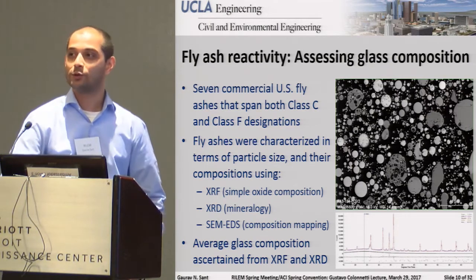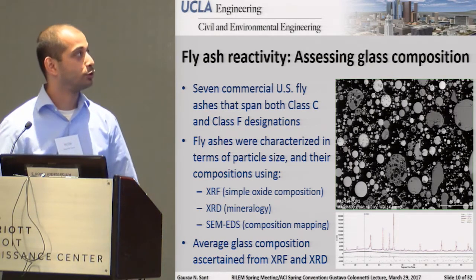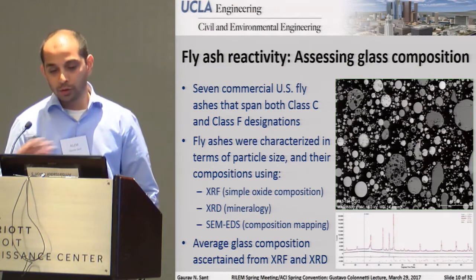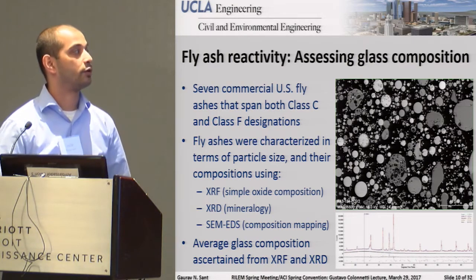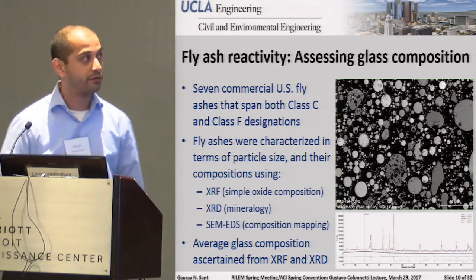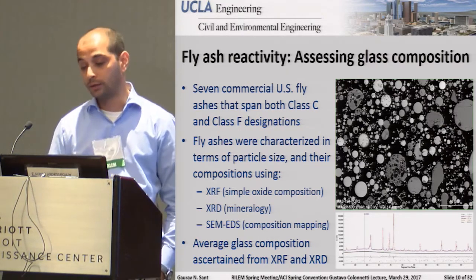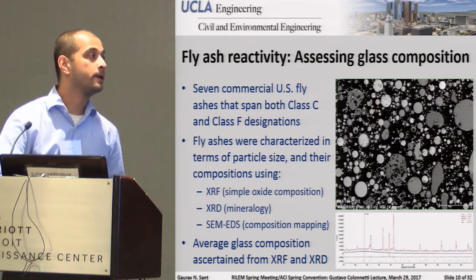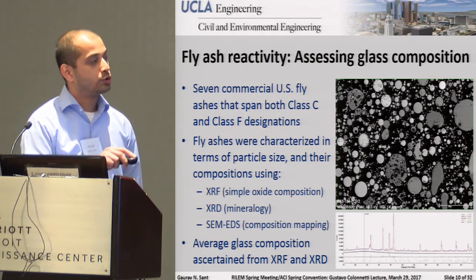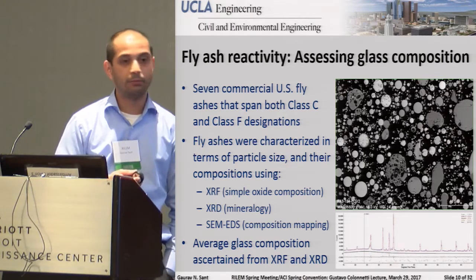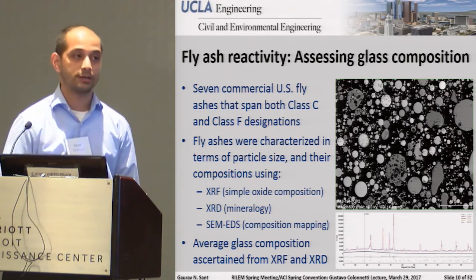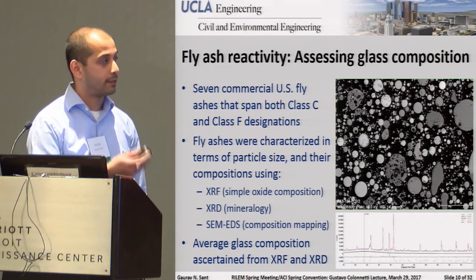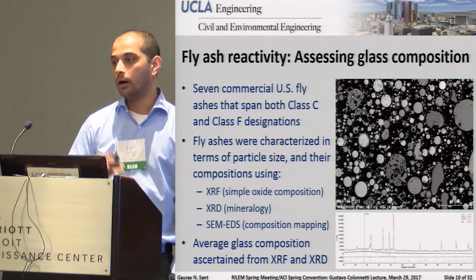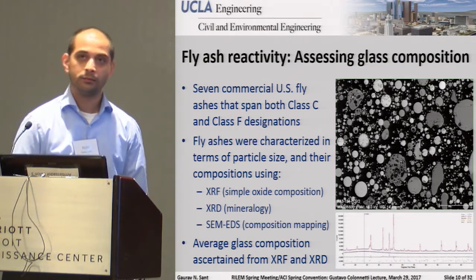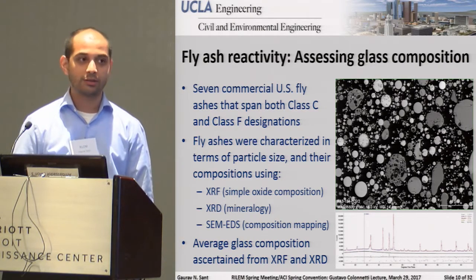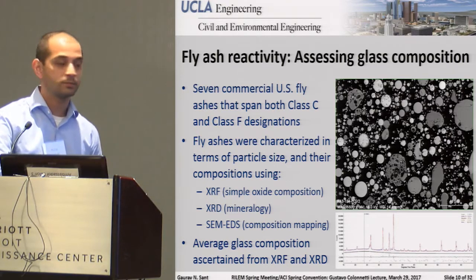But that in itself identifies one of the failings of the compliance-based approach. But we looked at these fly ashes and we went through what everyone else would do. We looked at things like X-ray fluorescence, we looked at the mineralogy of the fly ash using quantitative diffraction, we looked at compositional mapping using energy dispersive X-ray spectroscopy, and spent quite a bit of time trying to use the XRF, the X-ray fluorescence, the simple oxide data and the mineralogical data to be able to determine what the average glass composition is. Now, we do appreciate, since we do have quite a bit of the SEM data done, this was work that was originally done by Ryan Chancey, Maria, and Paul Stutzman, maybe about 5, 6, 7 years ago, something like that.